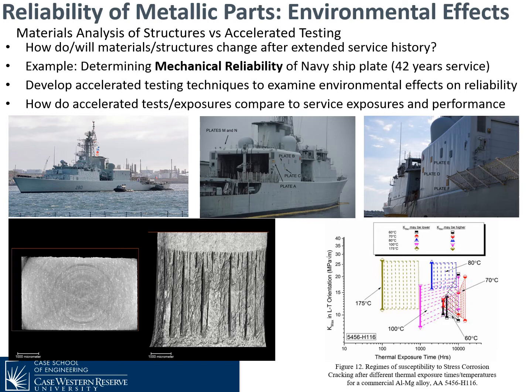In this case, we've also done fracture experiments, and what I'm showing here is a movie, and you are looking at the fracture surface of something that was tested in a sodium chloride solution. On the left-hand side, we have done tomography as a function of distance, and we're looking at the details of these splits on the surface. The other thing that we're doing, as I indicated with regards to the laboratory exposures, and this figure was in the summary document, we're looking at regimes of where laboratory exposures cause fracture and problems and where they don't.